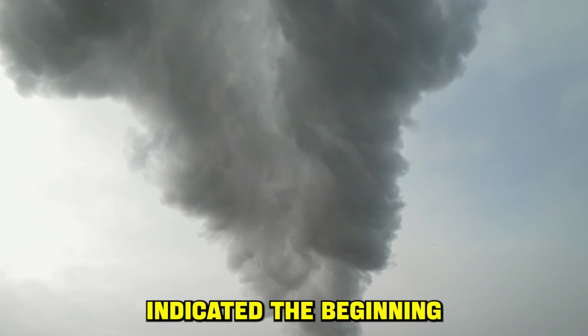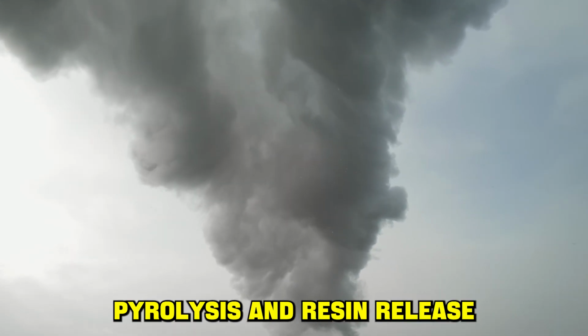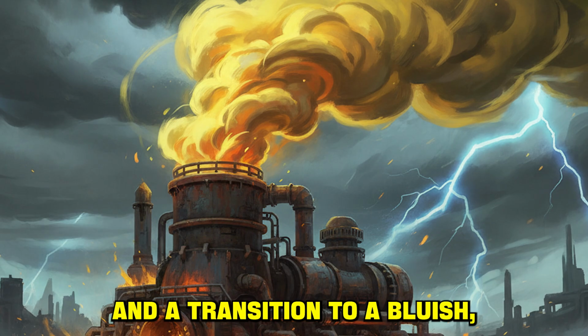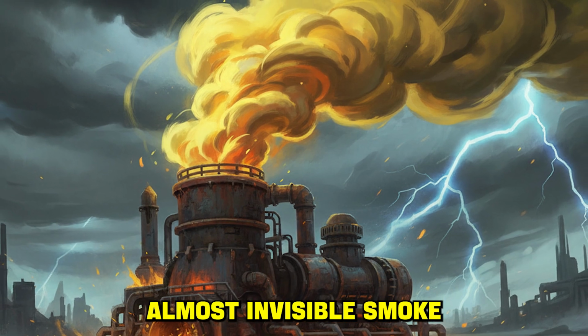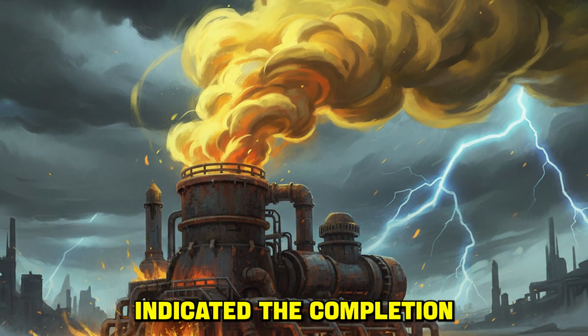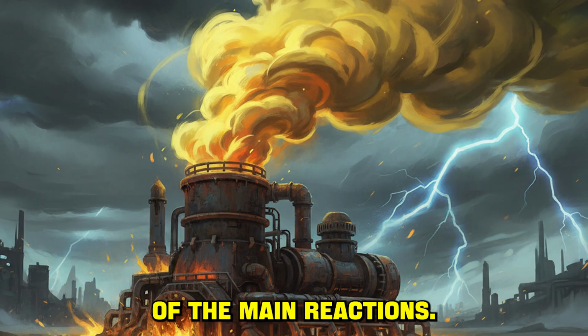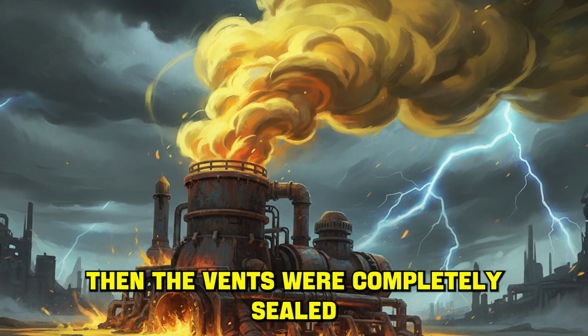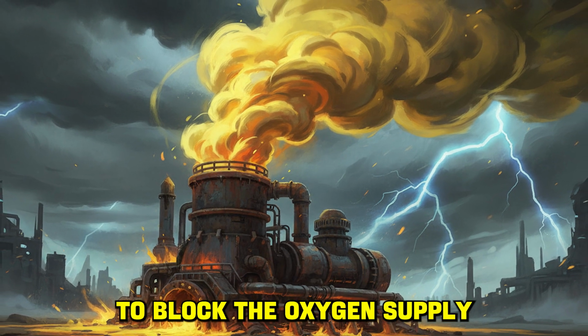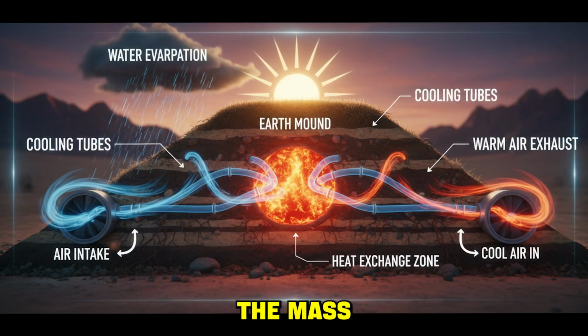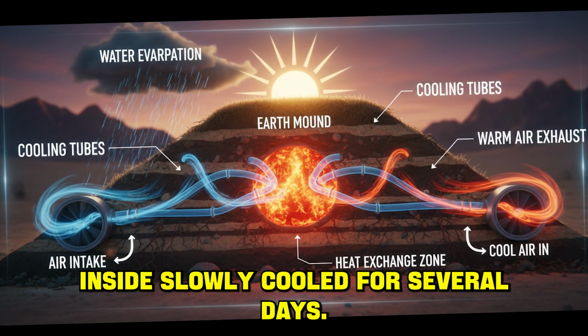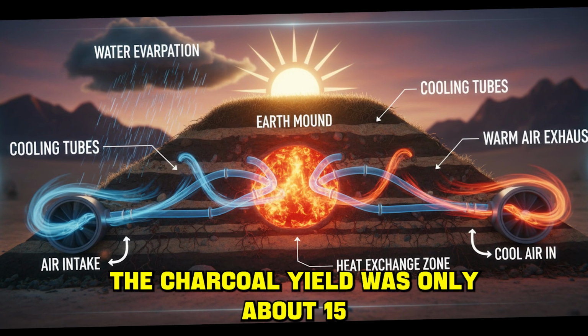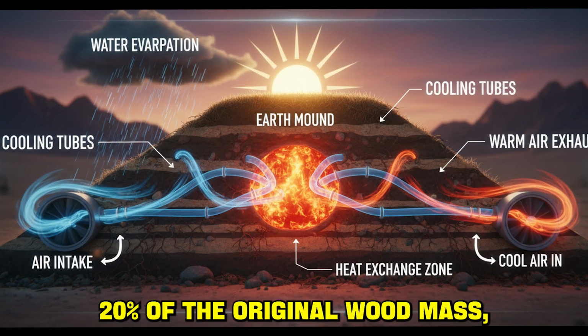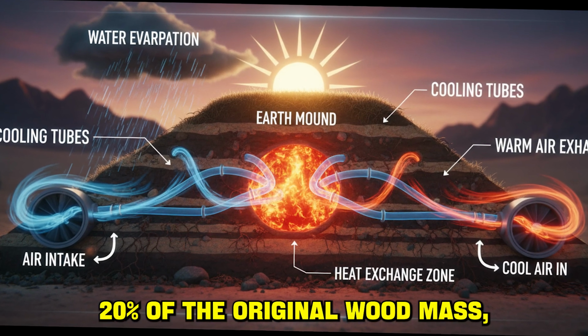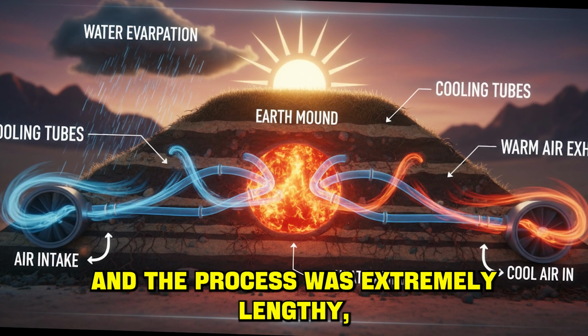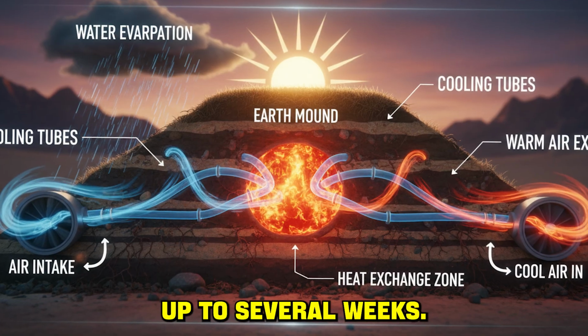Yellow smoke indicated the beginning of active pyrolysis and resin release, and a transition to a bluish, almost invisible smoke indicated the completion of the main reactions. Then the vents were completely sealed to block the oxygen supply and halt the process. The mass inside slowly cooled for several days. The charcoal yield was only about 15–20% of the original wood mass, and the process was extremely lengthy, up to several weeks.